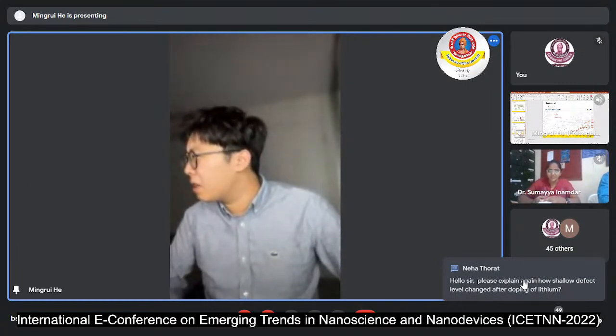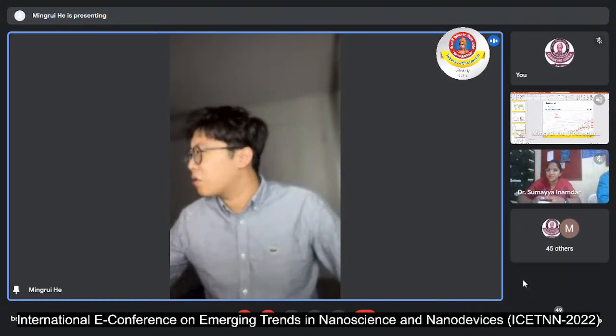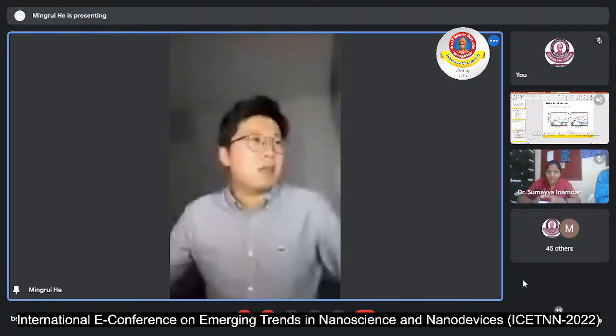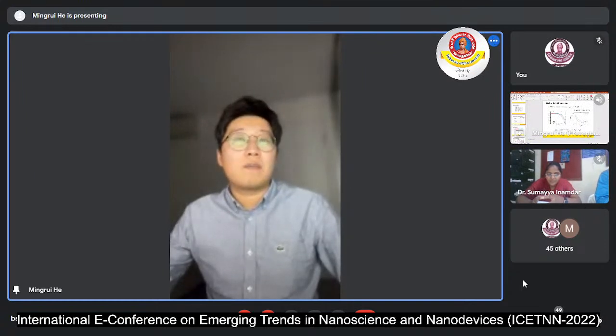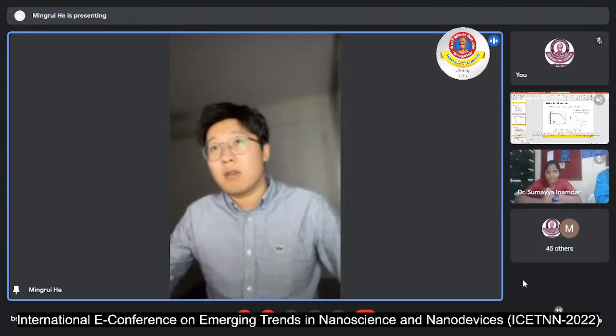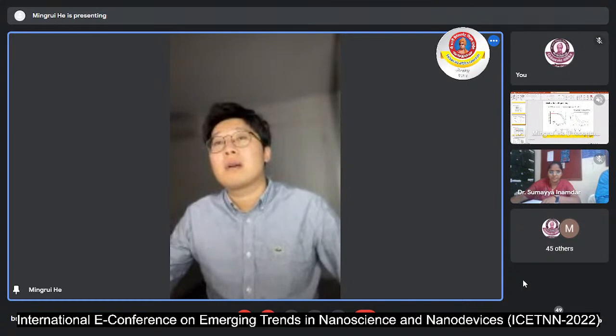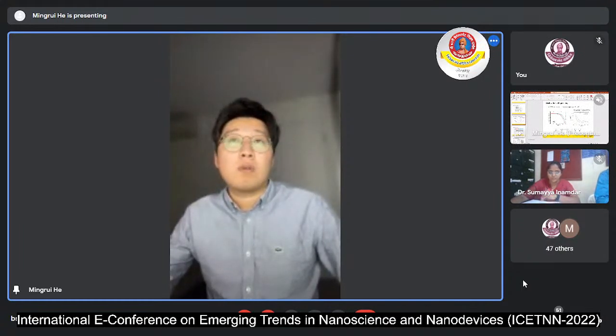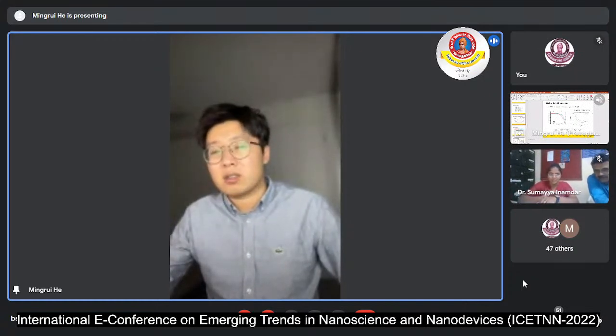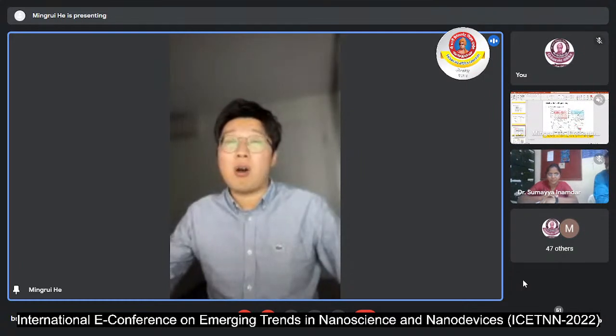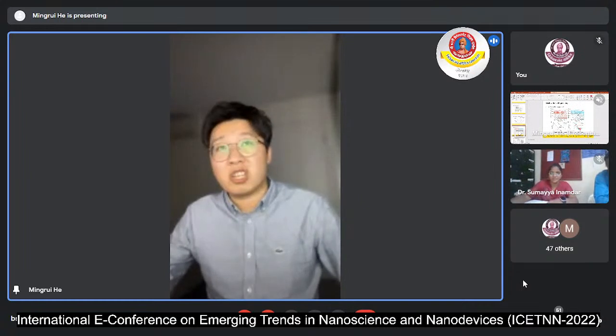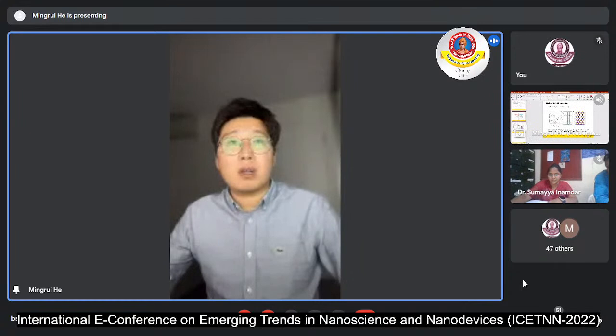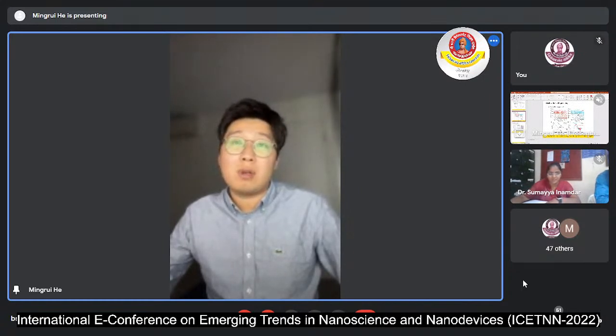Hello, sir. Please explain again how the shallow defect level changes after doping of lithium. Okay, probably I went a little bit hurriedly on this part. After we doped the lithium, the first thing we checked was that our conductivity was improved. When a property like the electrical property changes, it's normally related to some defect change. Following that, we calculated how the defects in the film changed by the admittance spectroscopy measurement. Here we get the capacitance, and after fitting this curve we can get two levels, one defect from each sample.